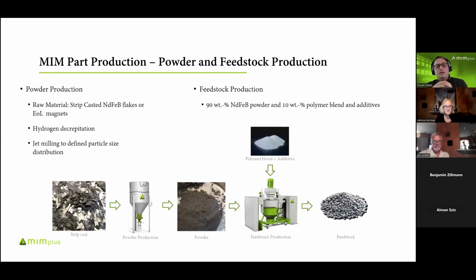This material is then transferred to a jet mill, where it is milled to a defined particle size distribution, and then we have our powder. The fun fact about the powder is that as soon as it comes into contact with oxygen, it ignites. So it's pyrophoric, which is really fascinating to see the first time, but of course it's unwanted. So we really need to make sure that we stay under oxygen-free conditions, especially with the powder.